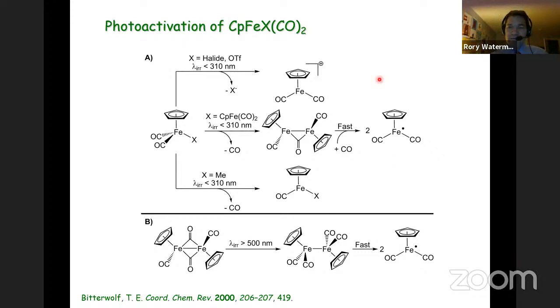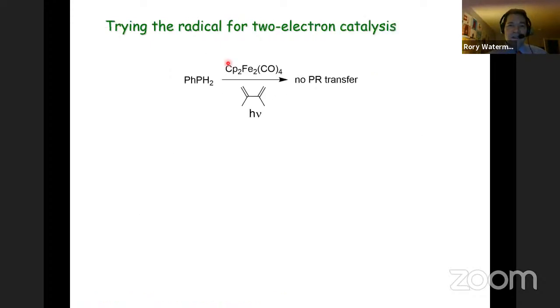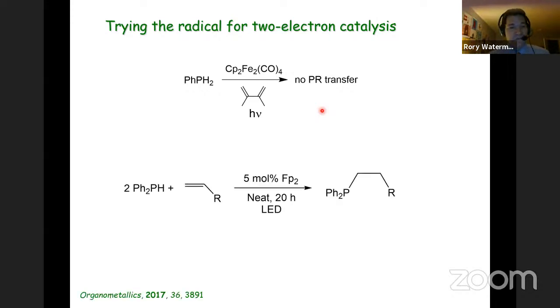And so rather than sort of thinking about what might be done with our reaction, we thought deliberately about generating that radical and what could happen there. And so again, we took the Fp dimer, which is actually the easiest way to get to the 17 electron compound under visible light irradiation. And that does not do phosphinidene transfer, but what it does do is hydrophosphination.